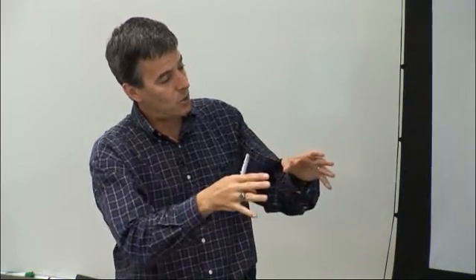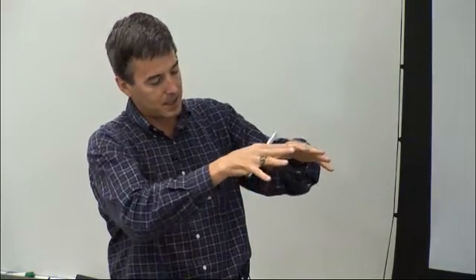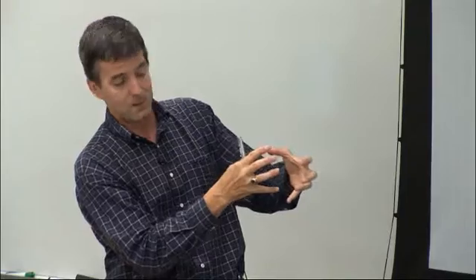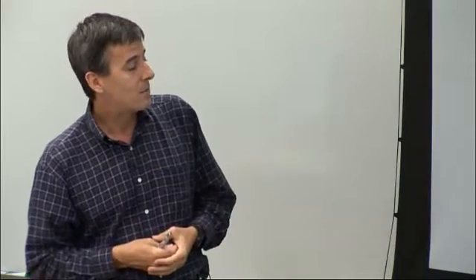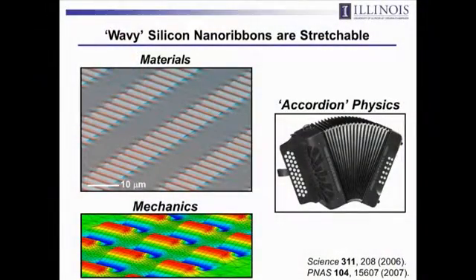Thin silicon looks pretty good, but not good enough, because this kind of characteristic is not what you want or you need if you want to get on the human body. So this is bending. What you really need is something that can both bend and also stretch, because if you only have bendability, then you can only wrap cylinders and cones. You can't even wrap a sphere, much less a brain or a heart. And you can't accommodate the kind of complex motions that organs are undergoing all the time either. So you need stretching. And there's no thickness to which you can make the silicon that will impart stretchability. So that may seem like a daunting problem, but even that one is really easy to overcome, it turns out.